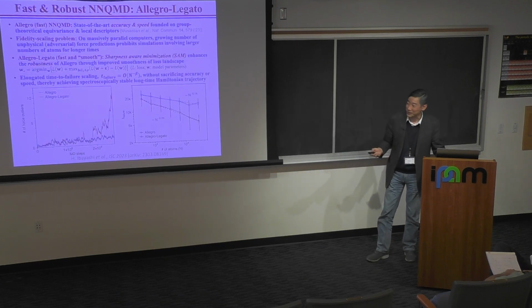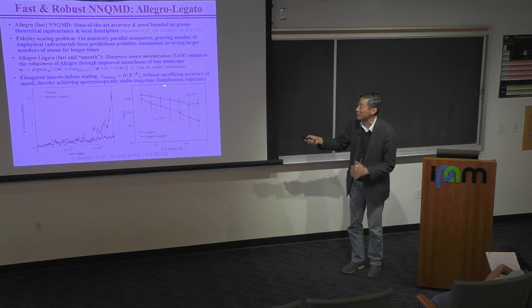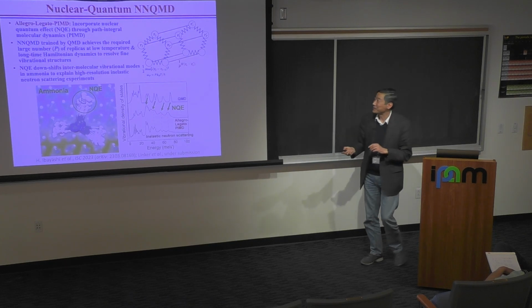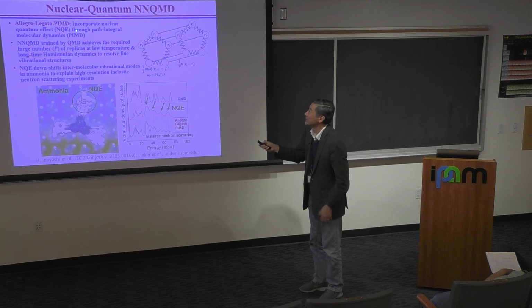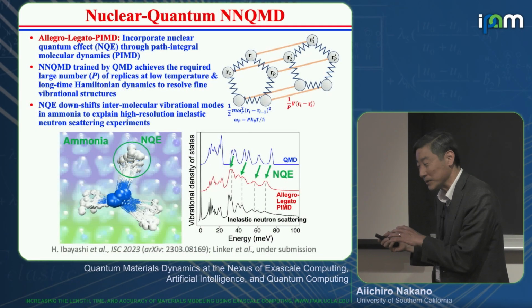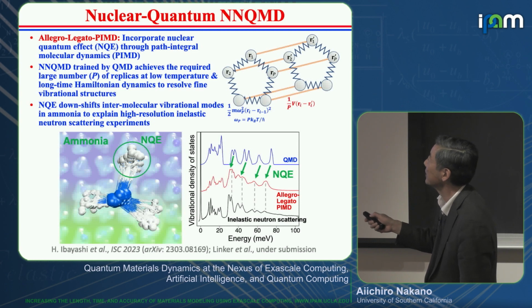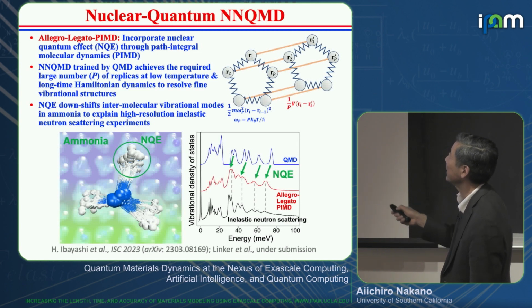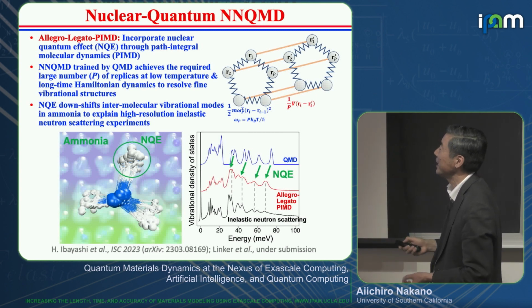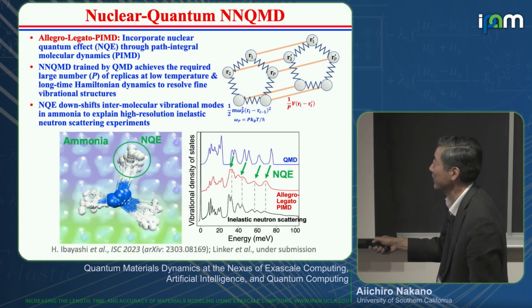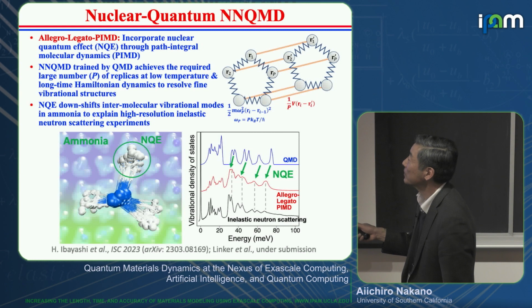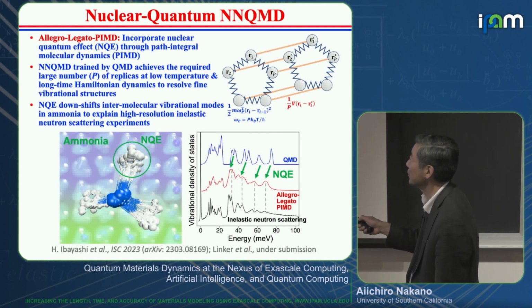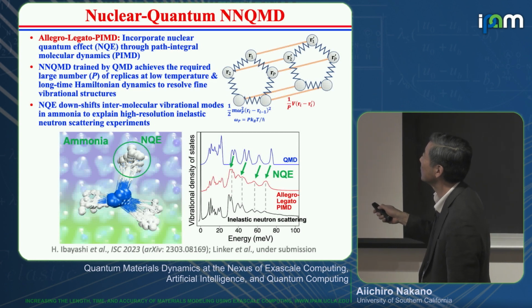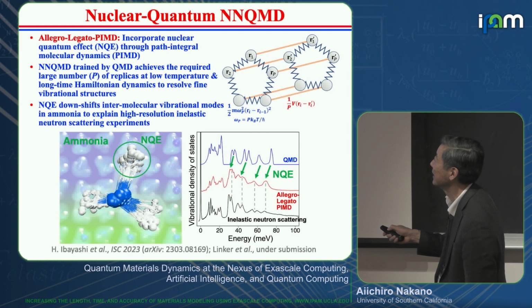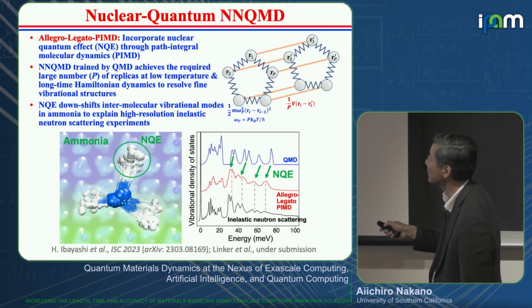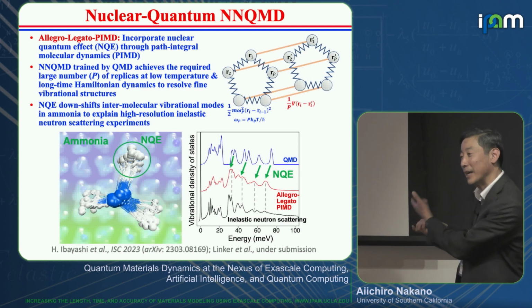So this is an example of what we call spectroscopically stable long-time Hamiltonian dynamics. We implemented nuclear quantum effects into neural network quantum molecular dynamics using path integral molecular dynamics like this. Each atom is a ring of beads, and that represents the nuclear quantum effect, especially for hydrogen. Neural network QMD trained by QMD achieved the required large number of replicas at low temperature. At lower temperature, you need a larger number of beads, and long-time Hamiltonian dynamics to resolve fine vibrational structure by Fourier transform.